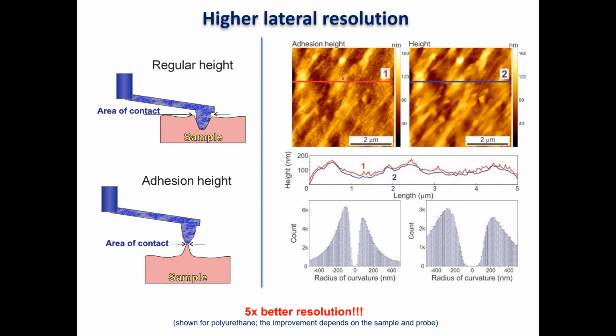And if you compare polyurethane surface, adhesion height and regular height, it's pretty small deformation because it's pretty rigid polymer, but still neck height is actually pretty substantial, and difference in area gives you resolution increase after all these calculations and measurements 5 times better. 5 times is pretty substantial, because at least this so-called super resolution Nobel Prize was awarded for 4 times increase. Well, that and optical microscopy, which is super popular.